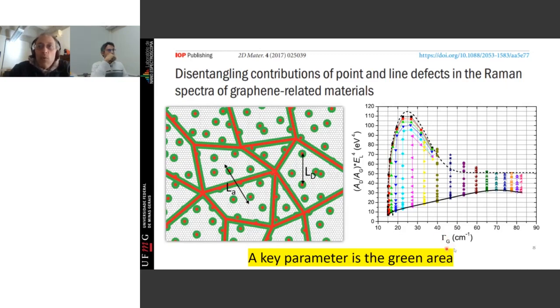If you look, for example, at the width of a Raman peak, we know the width of a peak is related to the certainty that you have on this energy. And when you decrease the certainty or you decrease the size of the crystallite, the peak broadens, okay? And here is again this defect induced D-band area. And with this two-dimensional plot, you can make a kind of phase diagram of amorphization that is, if your samples follow this line, it has only line defects. If it follows these lines, only point defects. And in the middle, you have everything as we have here, okay?